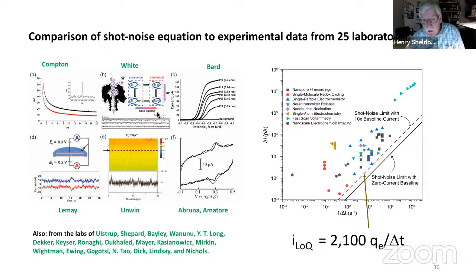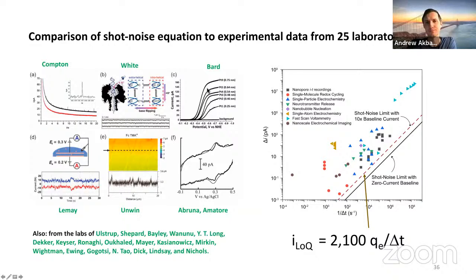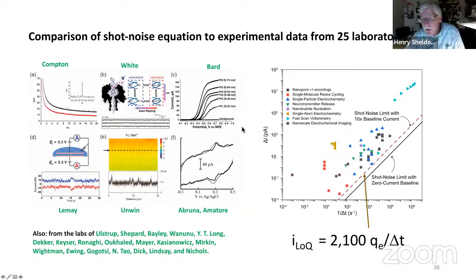I think the impurity question is similar for these types of measurements as it is for conventional measurements. The impurity question is sort of a lab to lab question and experiment to experiment. Some of these, the platinum clusters experiment, I always found this surprising. I mean, it works. But they're doing this in water. This is a perchloric acid solution, and you got impurities. You got some trace organics. You got trace other stuff, and diffusional transport of impurities to these small particles occurs in less than a microsecond. And it's always shocking that you can keep these particles clean enough to actually do these kinetic measurements. So I appreciate your concern, but it's hard to give a general answer to that.